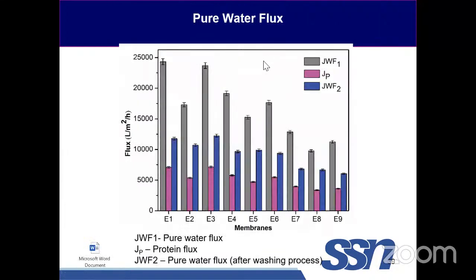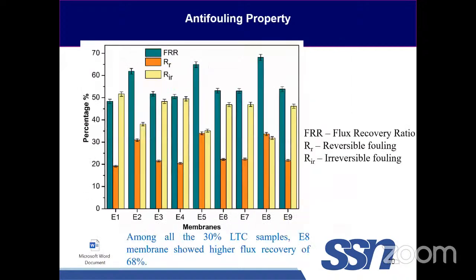Later on, we checked the pure water flux, the protein flux, and the pure water flux after washing. This is an important parameter which is used to measure the choking of the prepared membrane, where the 30% LTC incorporated membranes gave us good results in all the cases. And we checked the anti-fouling property of the prepared membrane. 30% samples gave good results. Among the 30% LTC samples, the E8 membrane showed a higher flux recovery ratio. As you can clearly see, the E8 membrane showed a higher flux recovery ratio.